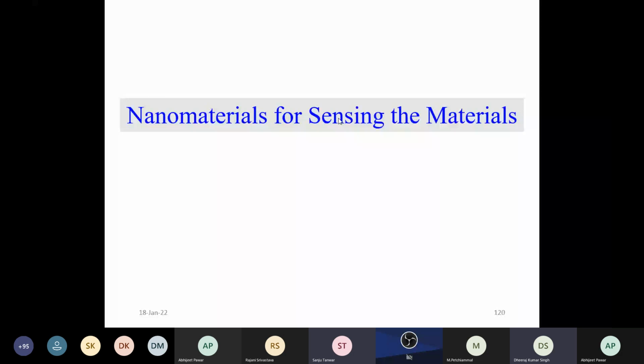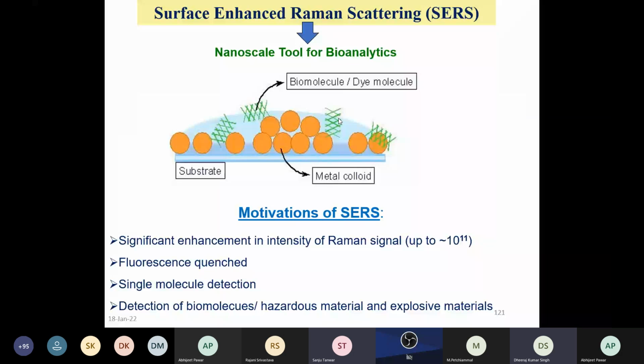I don't know if everyone has heard about surface enhanced Raman scattering or not. Raman got the Nobel Prize in India, and the weakness of Raman was that only one photon in about 10 million is scattered as a Raman peak, as it is a scattering technique. But fortunately, in the presence of metal nanoparticles, the Raman signal can be significantly enhanced. So a single molecule or atom can be detected, because the metal nanoparticle substrate enhances the Raman signal.